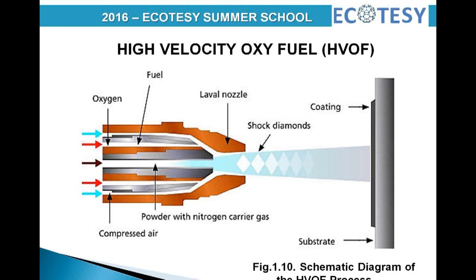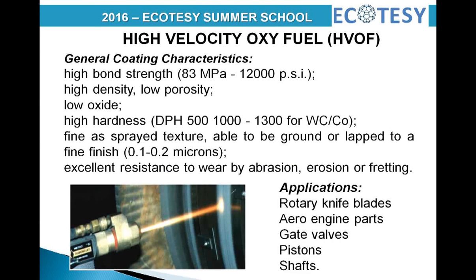Main applications of this process are rotary knife blades, aero engine parts, gate valves, pistons, and shafts. General HVOF coating characteristics are high bond strength, more than 83 MPa, high density, low porosity, low oxide content, high hardness, and a fine as-sprayed texture, able to be ground or lapped to a fine finish of 0.1 to 0.2 microns, with excellent resistance to wear by abrasion, erosion or fretting.